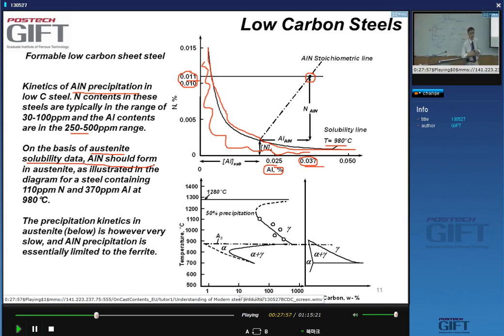However, it does not, because the kinetics of the precipitation of aluminum nitride are very low. So basically, even though the aluminum nitride is not very soluble in the austenite, when we process a low carbon steel in the hot strip mill, the aluminum nitride does not form.